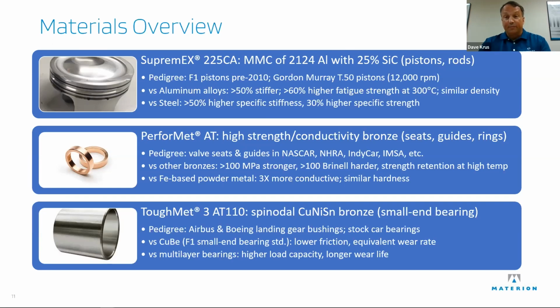We have tested it versus the copper beryllium that's standard in a lot of racing engines, small end bearings, and it works just as well as that. It actually has lower friction, the wear rate's about the same, and it is monolithic. It's not a coated material, so you can't wear through a coating and come up with a steel backing where the disaster happens. It's a slow, uniform wear rate.